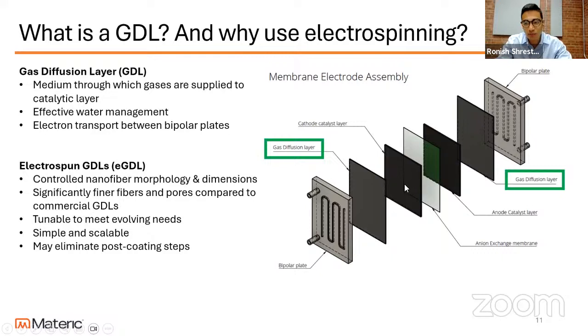And it's also responsible for managing the water within the cell to drive enough hydration to the catalyst layers while not letting the cell overflood. It also has the function of transporting electrons between the bipolar plates, and the nanofiber morphology of the gas diffusion layers significantly affects its function. So the nanofiber morphology also in turn significantly affects the entire performance of the fuel cell.